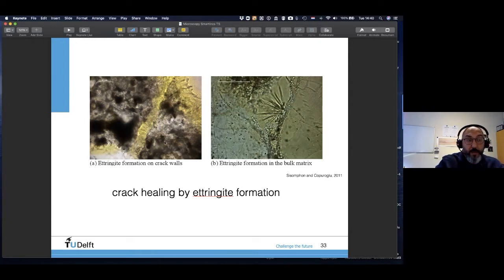And here you see the ettringite, the crystals I showed you just now, due to DEF or secondary ettringite formation. You can observe them, but you can also use their formation to your advantage for self-healing. We use the CSA type of additives in our cement paste to see their potential for self-healing, and you can observe that some ettringite crystals have the ability to close some very tiny cracks up to about 400 micrometers. We managed to heal substantially, but beyond that was quite difficult. But again, with these techniques, you can observe and identify all these needles of ettringite within your cracks.